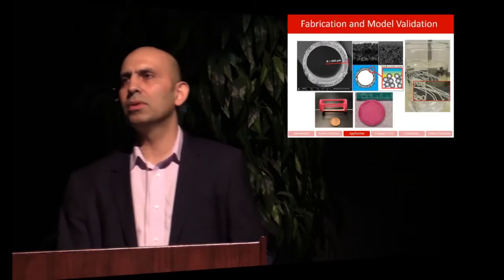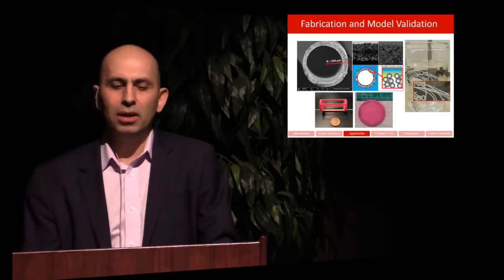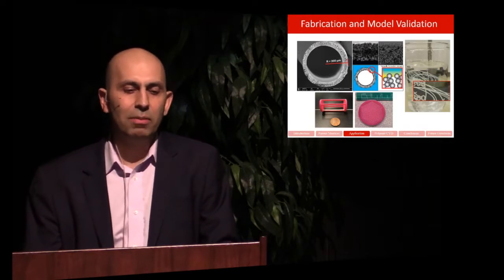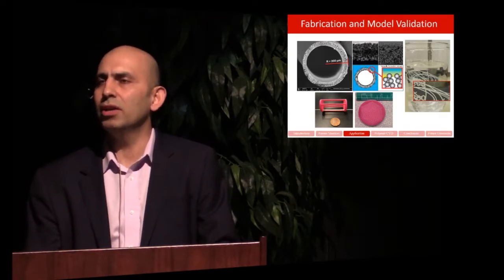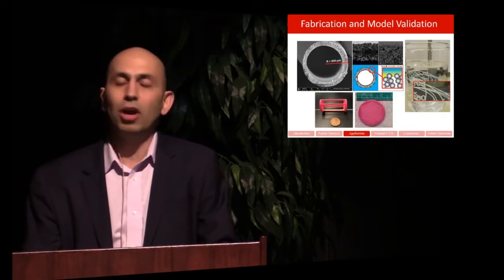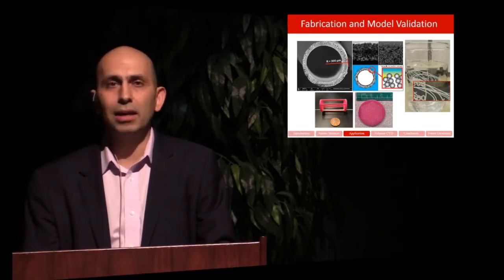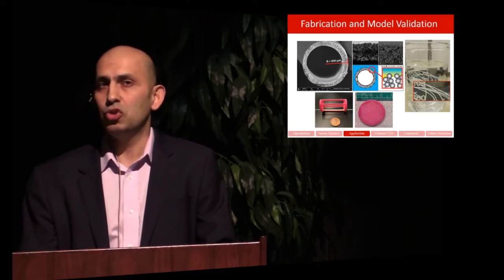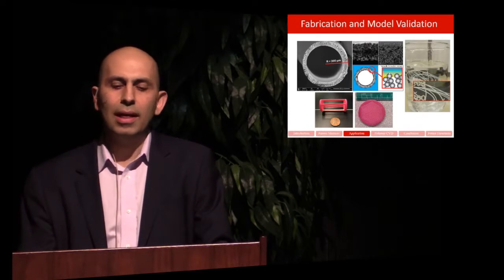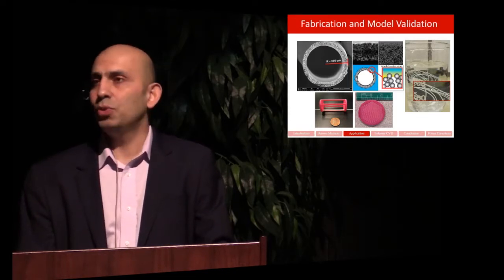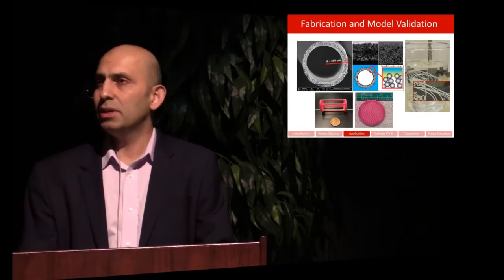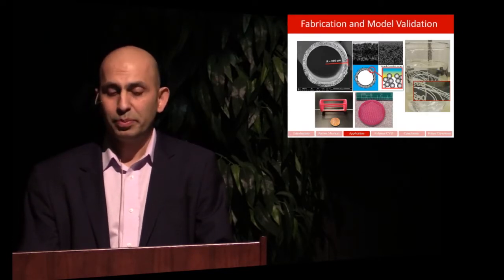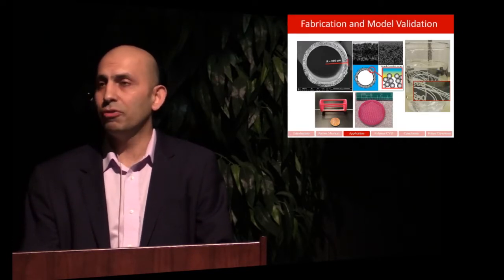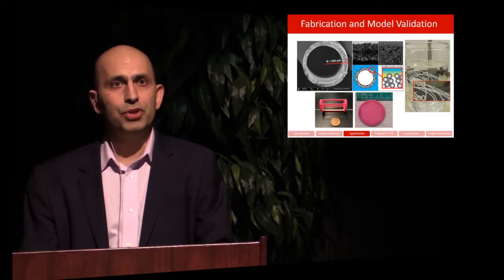So here's our attempt. We start making a membrane, basically a hollow fiber membrane. The thickness of this membrane is right in the range, 60 microns. The diameter is sized, so we know exactly how much it should be because we simulate the process. And then we can mass produce that if we want. And this has been done not for this specific material, which is hydrophobic, but for an ultrafiltration membrane.